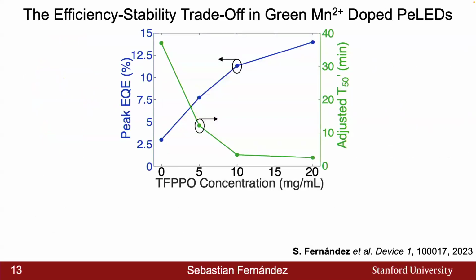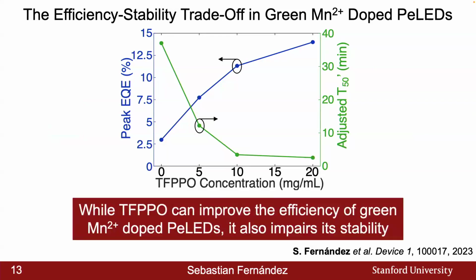And so now putting together the device efficiency characteristics of the champion efficiency devices and the adjusted T50 prime or the half-lifetimes of the champion stability devices, we see this interesting efficiency-stability trade-off start to emerge. And unfortunately, we see that, yes, TFPPO can improve the efficiency of these devices, but however, it also impairs its stability. Now, within the perovskite LED literature, this is quite rare. Usually when you have an improvement in efficiency, you either see a net neutral or net positive improvement in stability as well. So to really dig at this further, we look at conducting repeat electrical scanning measurements, as well as time-resolved photoluminescence decay measurements as well.